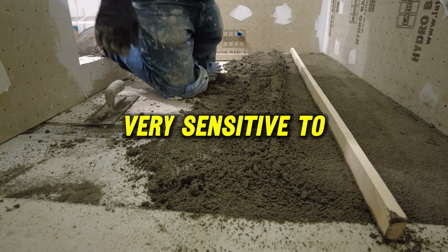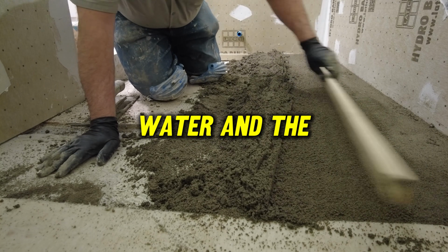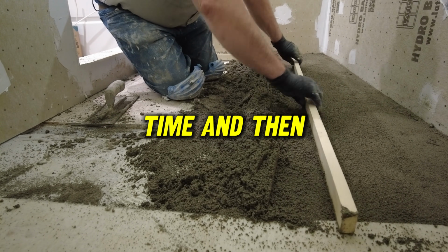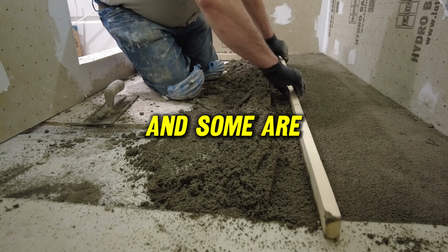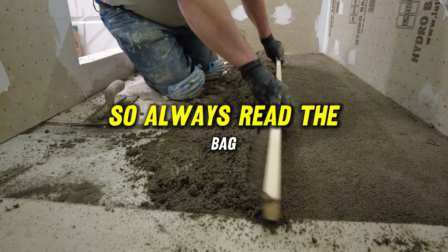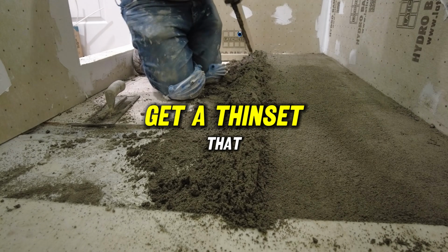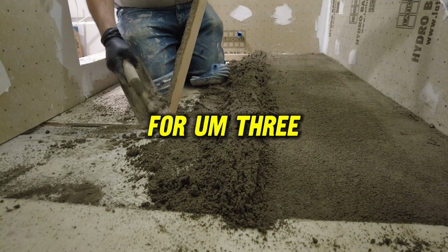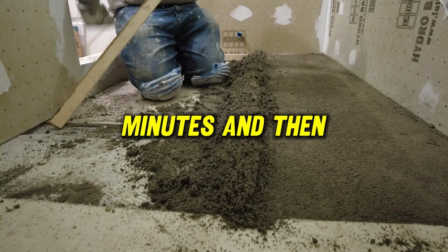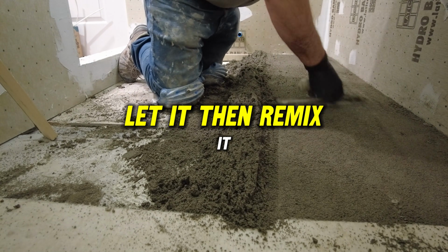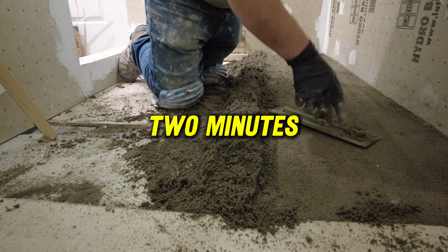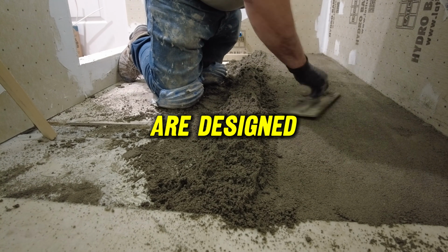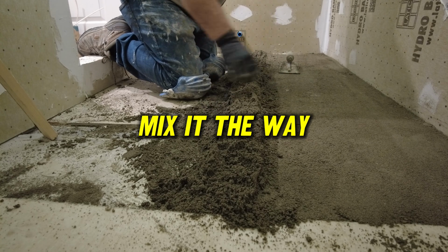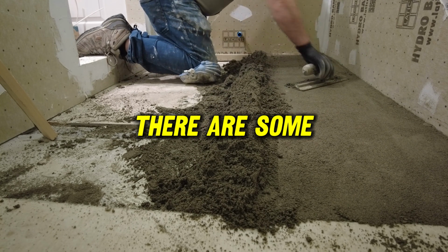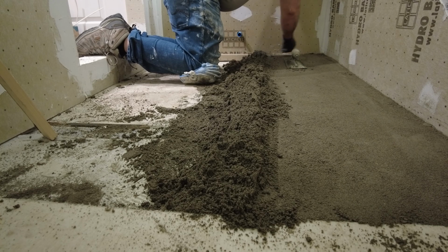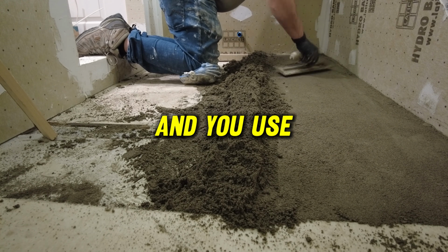Some are very sensitive to the amount of water and the mixing time and the slake time and then the remix time, and some are not quite as sensitive. So always read the bag. You might get a thinset that says mix it for 3 minutes and then let it slake for 10 minutes and then remix it for another 30 seconds or a minute or 2 minutes. To achieve the properties that are designed in that thinset, you should mix it the way it describes in the bag. There are some thinsets that you mix and you don't let them slake and you use them right away.